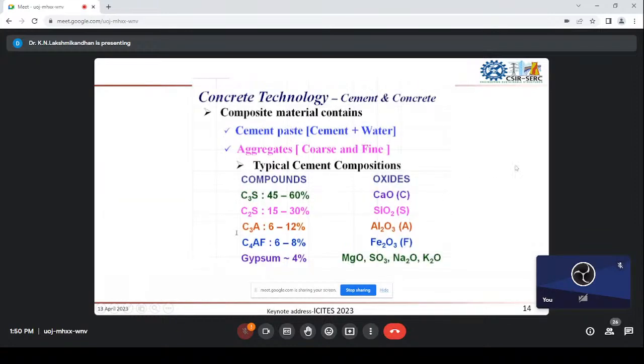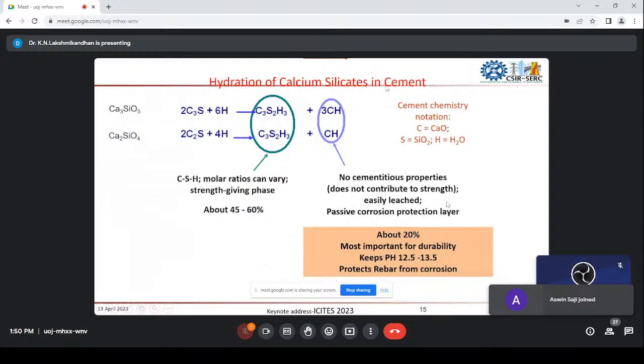If you consider that cement has a chemical composition of tricalcium silicate, dicalcium silicate, tricalcium aluminate and so on, these are all basic oxides available in the cement. This is the general hydration, the chemical reaction that happens when you add water to the cement. The product is the C-S-H, normally what we call the binder, and this quantity is normally around 45 to 60%.